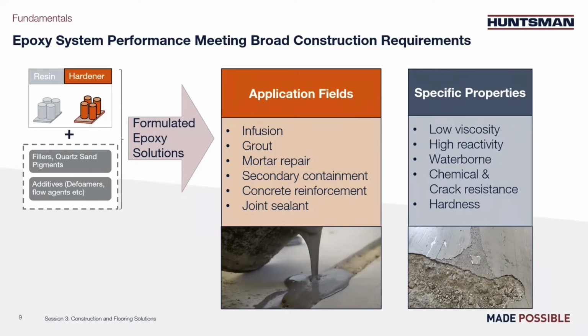Systems for other types of application are not so different from flooring. The concept is the same. You need a hardener, resin, filler, and additive. The process needs to be chosen, waterborne or not, for example. You might need a fast cure for repair or a good crack resistance, for example. Often, in this type of application, the system is designed to achieve a very low viscosity, enabling the addition of a large quantity of filler and higher strength. Many possibilities of hardener exist, and generally the challenge is to deal with fast cure, viscosity, acceptable pot life, and no VOC.